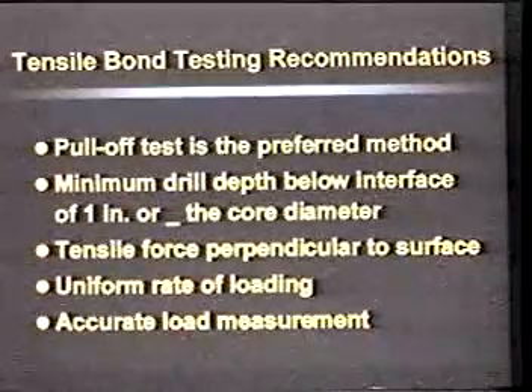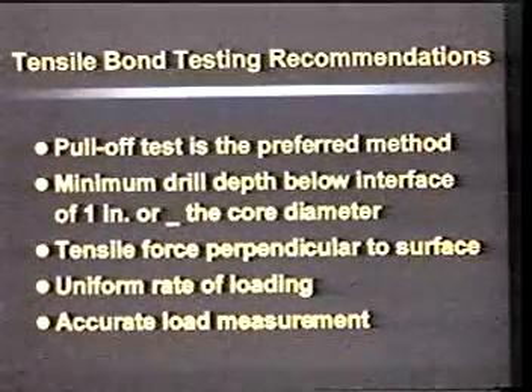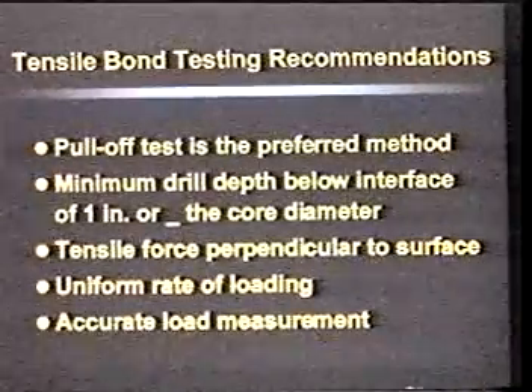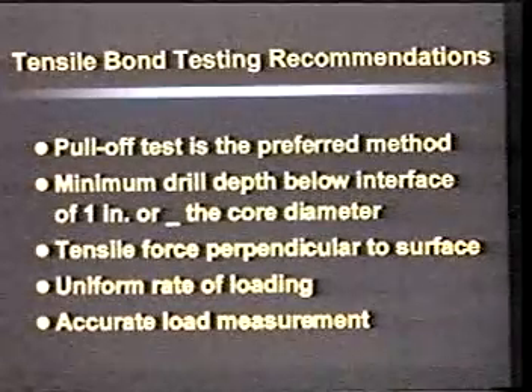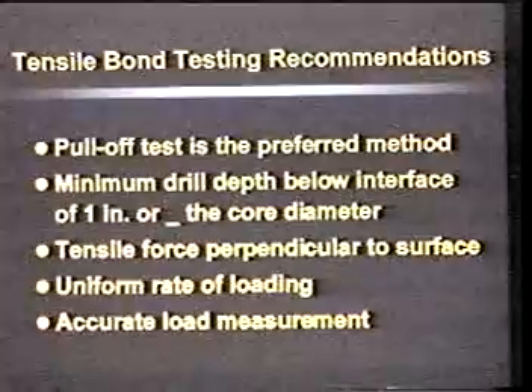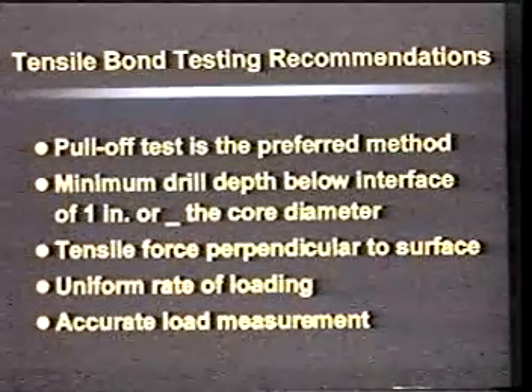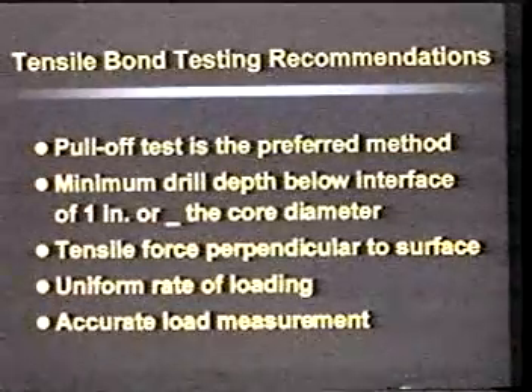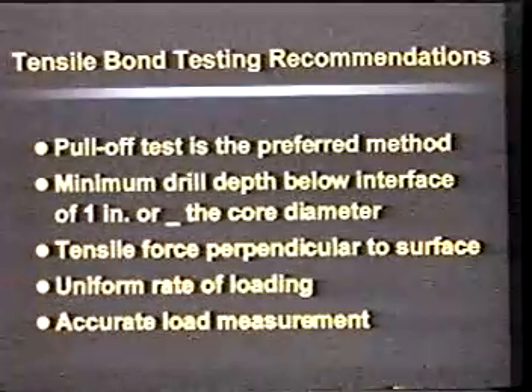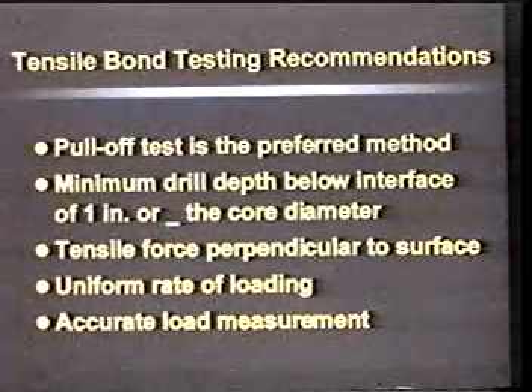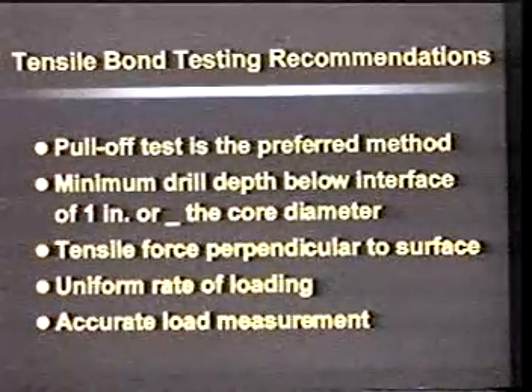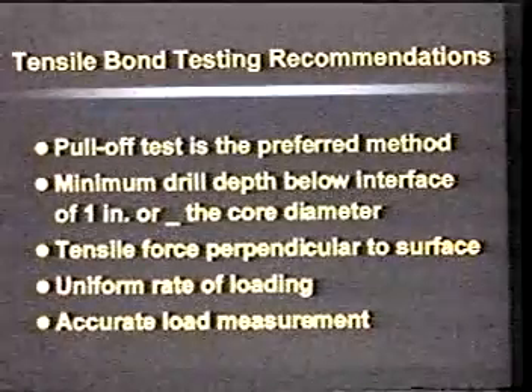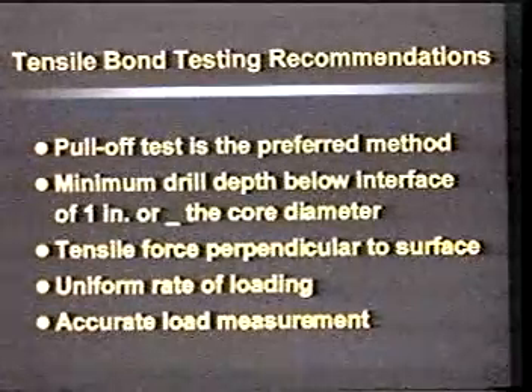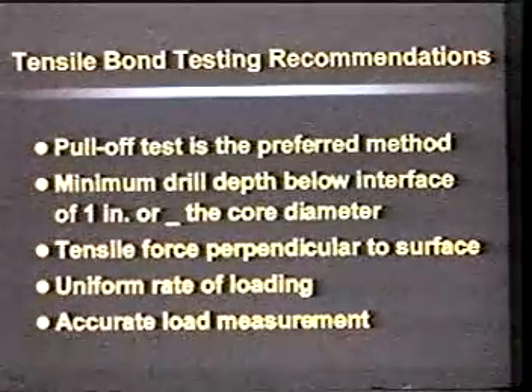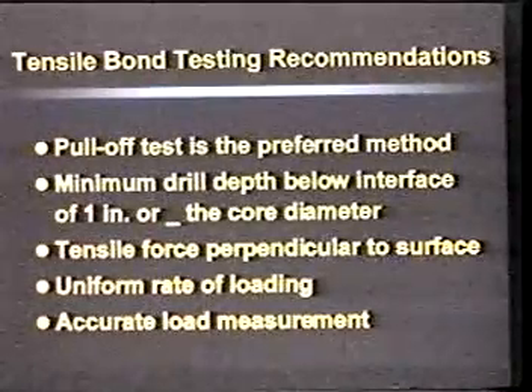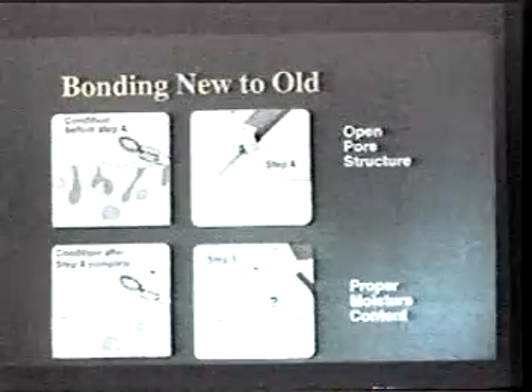Now, concerning the depth of drilling, in this study, which probably was the most extensive, to the best of my knowledge, we found that extremely important is the depth, which everybody else who studied found, but we found that it should be deeper, for instance, than in the existing European standards. It should be 1 inch or half of the diameter of the dolly we are using. Then we have a much more realistic picture of the effect of different factors and stress concentration than with shallow drilling into the substrate. Uniformity, which I was talking about.